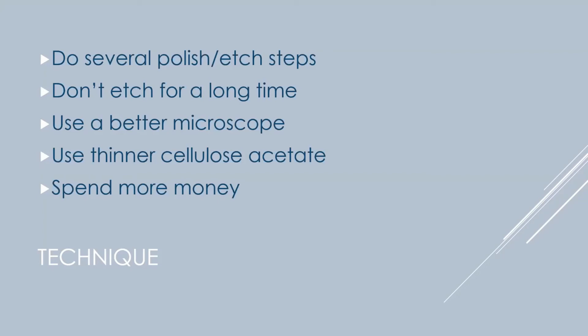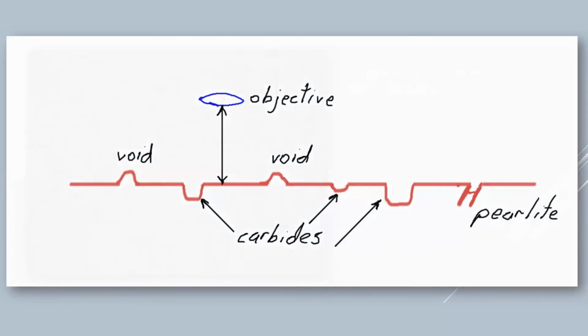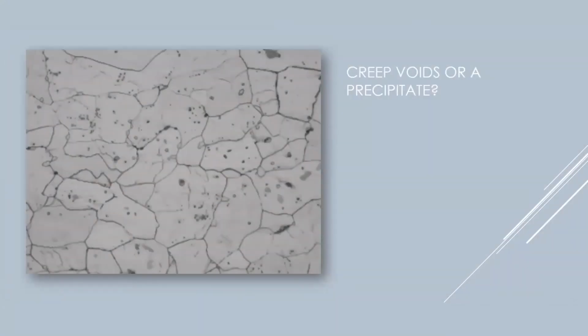And I wouldn't etch for a very long time either, because you saw the size of those particles. If I etch for a longer time, those grain boundaries get wider, and now I'm not going to be able to see those voids. So you have to do a very light etch, which normally we don't do, but you want that to show up those voids.